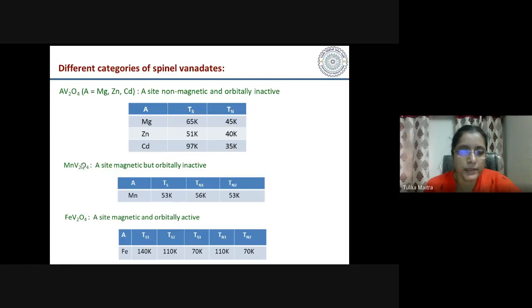Okay, so when the A site is magnetic but orbitally inactive, like MnV2O4, there we see that there is one structural transition from cubic to tetragonal phase, but 2 magnetic transitions, one from paramagnetic to collinear ferrimagnetic state, and then from collinear ferrimagnetic to non-collinear magnetic state at a lower temperature.